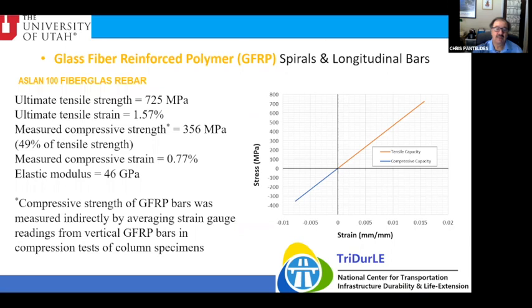So what are the properties? We've tested them. The ultimate tensile strength is 725 megapascal, and it is a linear elastic material. Ultimate tensile strain is 1.6%. And the compressive strength, we measure it indirectly, about 49% of the tensile strength.